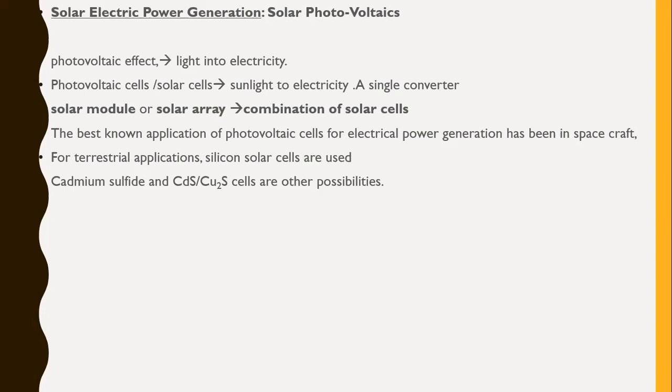So far, efficiencies have ranged from 3 to 8% for these cadmium sulfide cells, and these cells have been less durable than silicon cells because there is degradation with exposure to oxygen, water vapor and sunlight, especially at elevated temperatures.